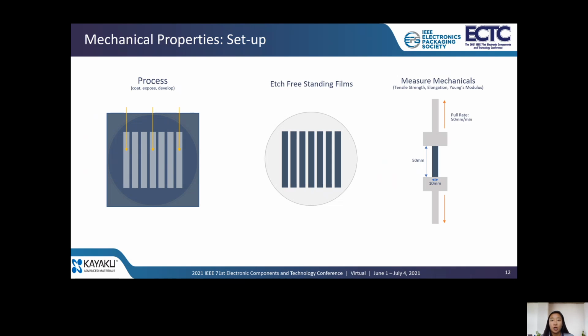What's not shown here in this final schematic is that we actually use an additional holder to help aid the difficult process of aligning the fragile film onto the Instron before testing. Each of these films is around 100 millimeters long by 10 millimeters wide, and we use a 50 millimeter gap and pull at a 50 millimeter per minute rate to measure the mechanical properties. As you can see, the process is probably the most difficult and tedious part out of everything, which really leads to high variability, especially in our elongation values.